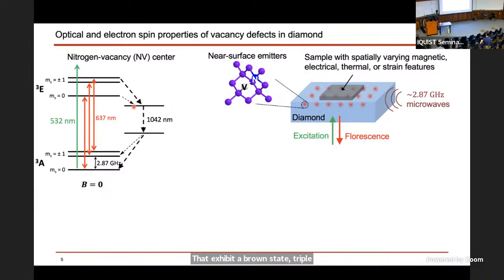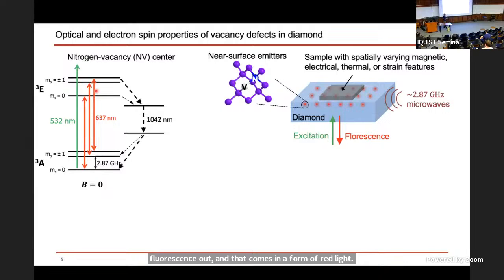So this is the corresponding energy level diagram, for which the ground state is a triplet with spin states ms 0 and ms plus or minus 1. It is optically active, which means that if you excite these unpaired electrons with, for example, a green laser, but basically you can do this with any above band excitation, across this pure optical transition you get fluorescence out, and that comes in the form of red light. The pure transition is at 637 nanometers, and we call that the zero phonon line.